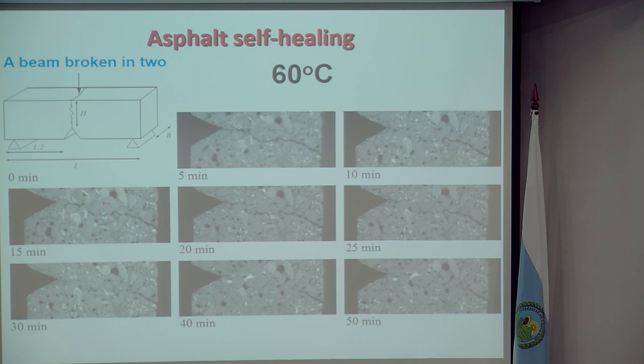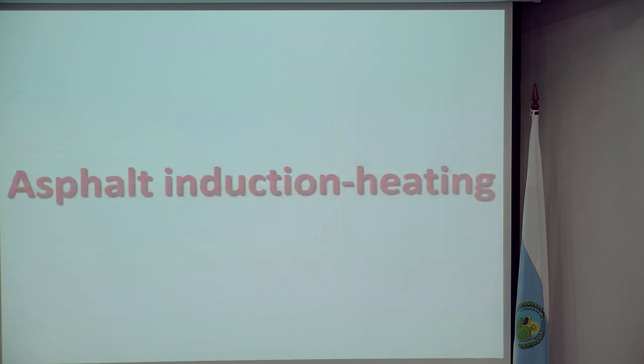Obviously, our roads are not at 60 degrees C, so we had to look at approaches that would help that phenomenon or speed it up. And so we've looked at two approaches. The first one is using induction heating, so some kind of magnetic field, and using the fact that if we put in materials that are going to react with that change in magnetic field in terms of induction, we can locally heat our material quite high.